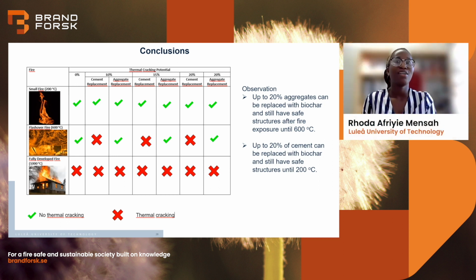All right. So we made a summary of the fire behavior of biochar concrete and compared it to the standard concrete using the respective temperatures we used in this project. So at 200 degrees Celsius, which represents a small fire, we saw that none of the samples experienced thermal cracking. And at 600 degrees Celsius, which represents flashover fire in structural fires, we saw that all the cement replacement samples